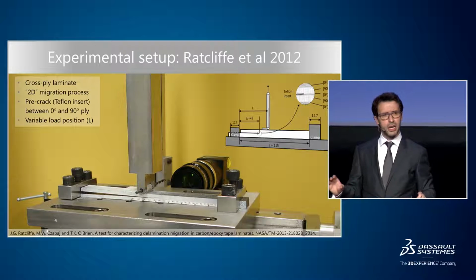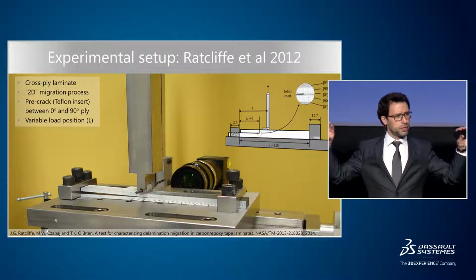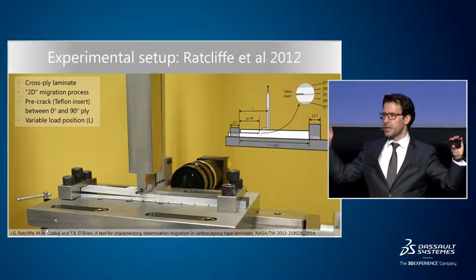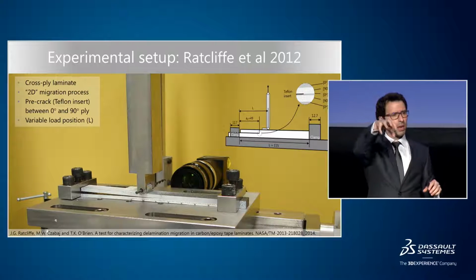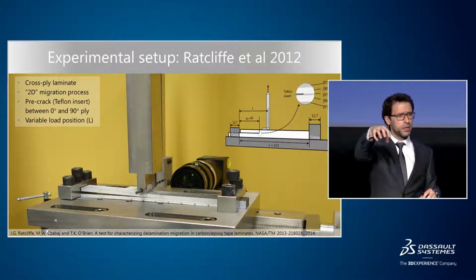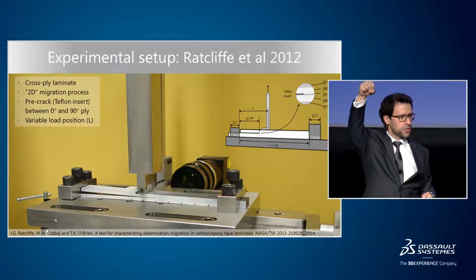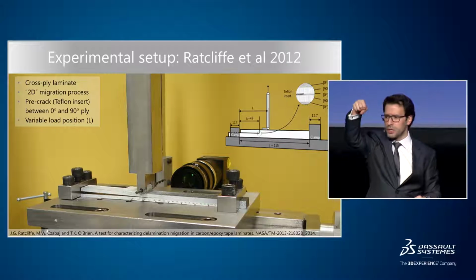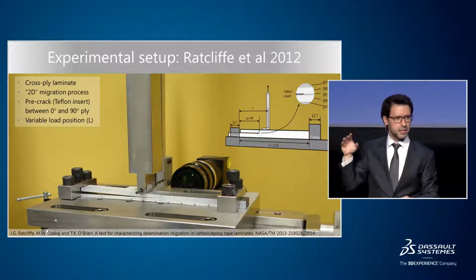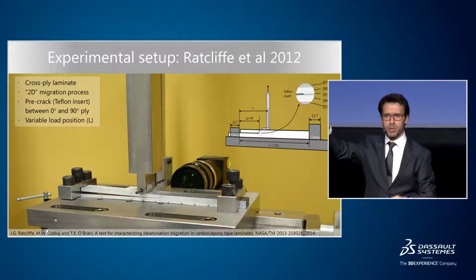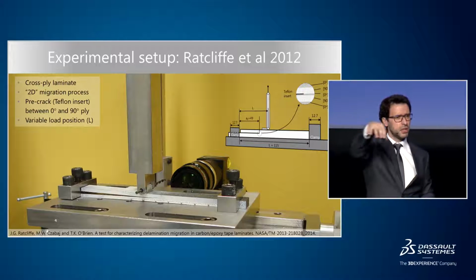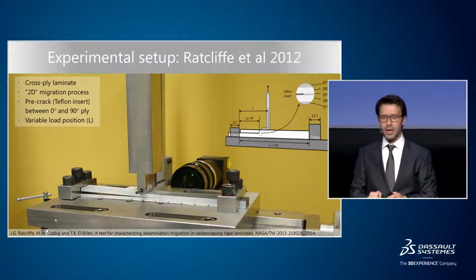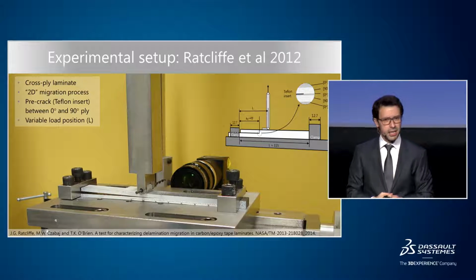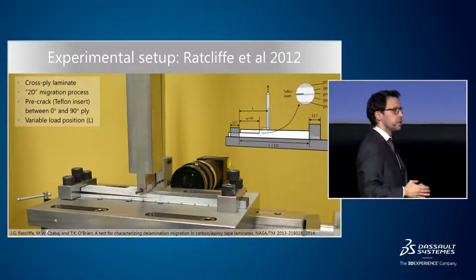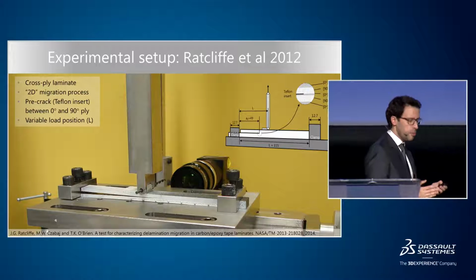And what they've done here is to fix the bottom part of a composite specimen at both ends and then apply somewhere along the middle a vertical load upwards. And the position of this vertical load, which is characterized by distance L in the screen, is a variable distance. So you could do that at a certain distance or do it at a different one. And what happens when you apply that force is that the crack grows in a very peculiar way.